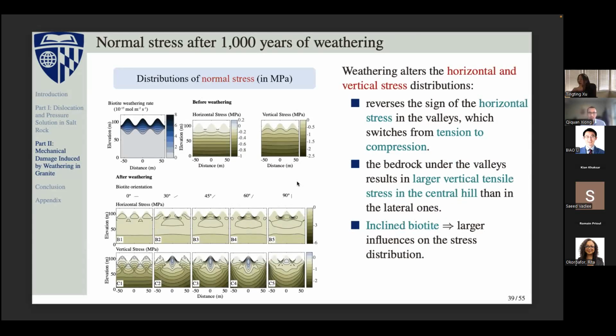And we also want to see how the stress is altered after this weathering. If we compare the results before weathering and after weathering, the top figure and the bottom figure, we can see that the biotite weathering indeed altered the distribution of the stress, either the horizontal stress or the vertical stress. Because the stresses that we apply on the boundary of this system are constant, this stress alteration is driven by the biotite weathering and the microcrack propagation. And with different biotite orientations, we get different patterns of the horizontal stress and vertical stress. With the vertically aligned biotite, we get more alteration in the stress distributions. So that's all for the simulations above. It's a simulation where we predefine the weathering pattern.